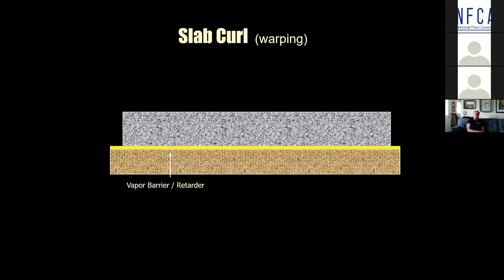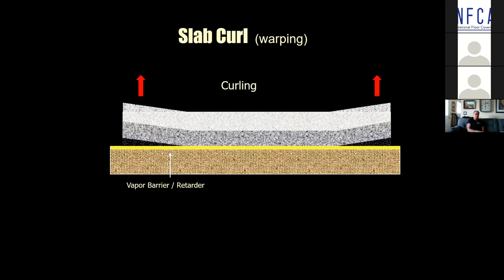Remember now, this mass of concrete that's on the ground, here it's on a vapor retarder, half of the water that's in that concrete slab is not chemically combined and is going to leave over the course of time by evaporation. And as long as that surface is open and it continues to lose moisture, volumetric change is occurring at a greater rate in the upper half of the slab than in the lower half of the slab. And when this happens, the edges of the slab, usually about maybe 3 to 4 feet each side of the joint, warp. And it's a huge issue.